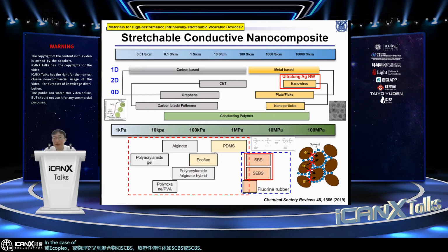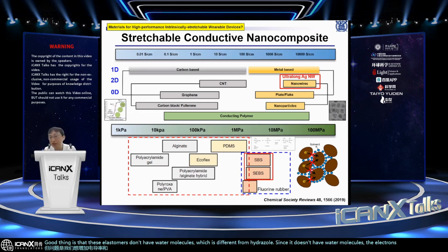In the case of chemically cross-linked polymer like PDMS or Ecoflex, the good thing is that since those elastomers are based on covalent bonding, material durability is really, really nice. Although we implant the PDMS in the body over a long-term period, its original mechanical property or material property can be maintained. So PDMS has been used as an implant for plastic surgery over a long-term period. But the problem is that we want to increase the conductivity. And the good thing is that these elastomers don't have water molecules, which is different from hydrogel. Since they don't have water molecules, the electron can be transported easily following the percolation network of the conducting fillers.